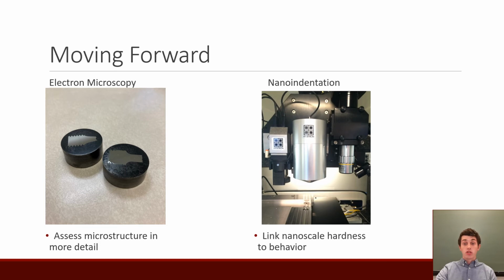Another place that this research could be progressed would be going to nanoindentation. This would let us link the nanoscale hardness to the behavior at the macro scale. And additionally, we could measure the hardness near key features in the metal. One of these would be to look at the differences of grain boundary hardness, considering the different ways that the delta phase forms. Another, more related to the current research, would be looking at the niobium carbide particles. We could look at the hardness of the specific particles to see if they're significantly harder or softer than the regular metal. In addition, we could look at the areas around it.